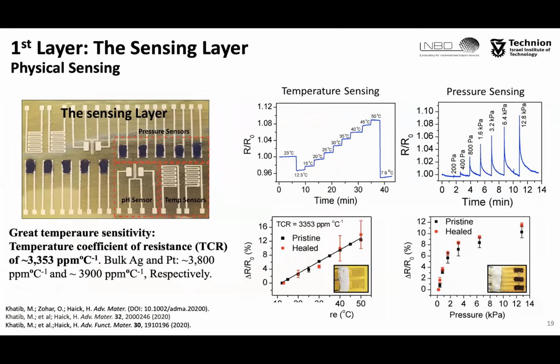For temperature sensing, we used a resistive pattern of silver nanowires embedded within the new self-healing polymer. We found that the self-healing structure and the self-healing temperature sensor were very sensitive both before and after recovery from structural damage. Even after a complete cut, we could get back to the original values of temperature sensing.